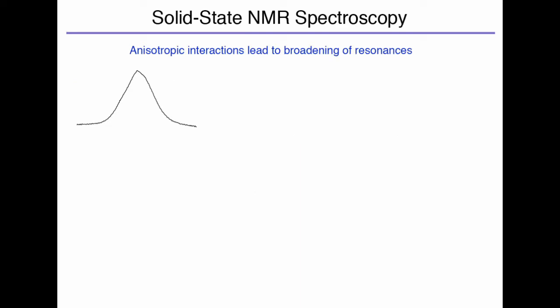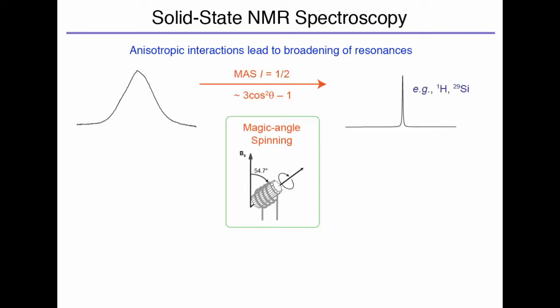So we know that the anisotropic interactions, the directional interactions, are causing us to get these very broad resonances. We know that in solution state, because of that rapid molecular tumbling, we can narrow those lines. So why don't we just mimic that in the solid state? And that's exactly what we can do, using a technique known as magic angle spinning. So we take our sample and we pack it into what's known as a rotor. And we align that rotor at what's known as the magic angle, which is 54.7 degrees. And then we spin that sample really, really quickly to mimic that solution state that we know works really well.